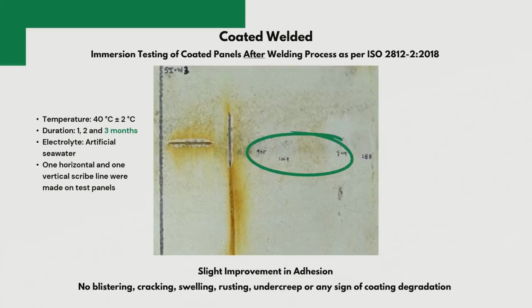The pull-off strength, interestingly, in Amal's report, I think we showed you, yeah, here it is right here. One of the things that she commented on was that the pull-off strength actually went up over time, which surprised us too. We didn't expect that either. What's most important to realize is that pull-off isn't an indicator for this technology the way that it is for polymer coatings. What's really important about pull-off for polymer coatings is its resistance to osmotic pressure. That's why we do pull-off tests, and it's a very important thing for barrier coatings.